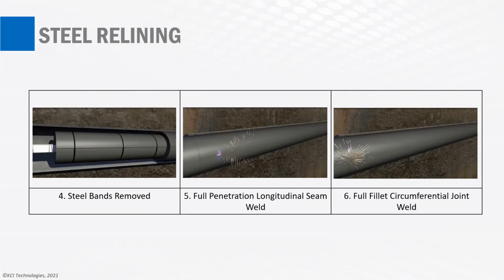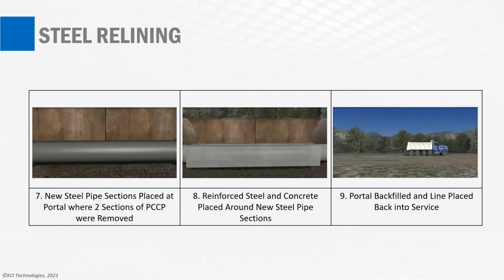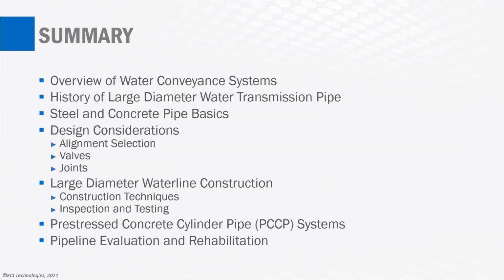If you ever get the opportunity, you should experience it. It's like a nuclear explosion inside the pipeline once the steel bands are cut and the cylinder actually opens back up. Once it's opened back up, it's fitted. They apply full penetration longitudinal seam welds and full fillet circumferential joint welds also. Once this is done, in the portal where the 2 PCCP sections were removed, they now replace that with 2 new pieces of steel pipe, put that within reinforced steel and concrete, and then fill the portal back up. One last thing that they do with these relining systems is they then go back in and actually apply a cement mortar lining on the inside.